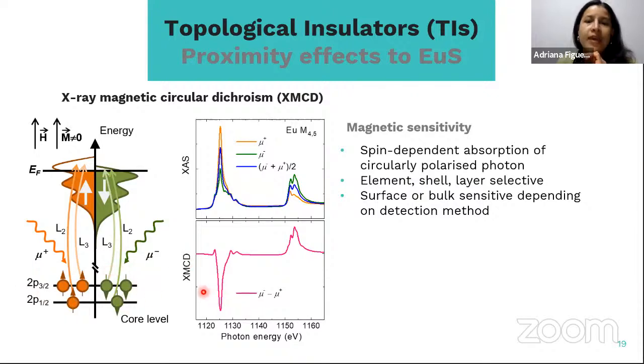It is also based on a spin-dependent absorption of the circularly polarized photons that we shine on the sample. With this technique, we focus the energy on the magnetic elements in a material, and not only the magnetic elements. For example, in this case, for the TI, we are interested in looking not only at the magnetism of the europium elements in the europium sulfide, but also at the magnetism of the non-magnetic elements, because of these claims of induced magnetism that has been reported in the bismuth selenide or bismuth telluride topological insulators.